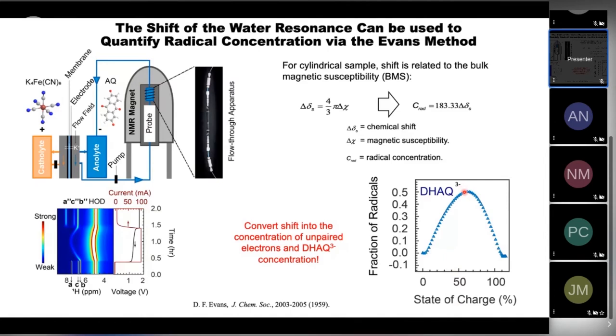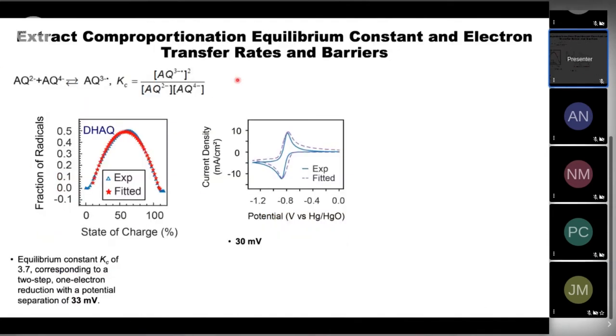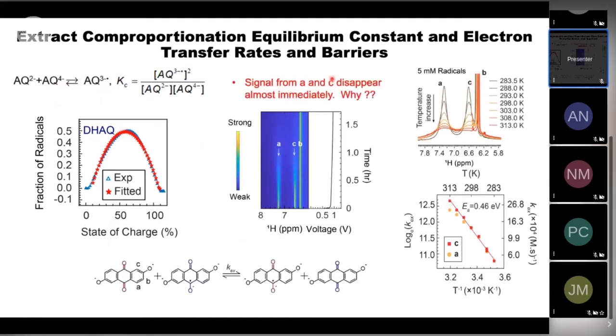50% of concentration. And that's because the chemistry is complicated. You end up with these comproportionation reactions where the radical disproportionates into the two diamagnetic components. And from that, we can actually work out the equilibrium constants of the processes, and it rationalized the CV. There's another interesting thing, and that's why the signals disappear almost immediately. And this is due to electron transfer processes that occur between the radical and the diamagnetic species.